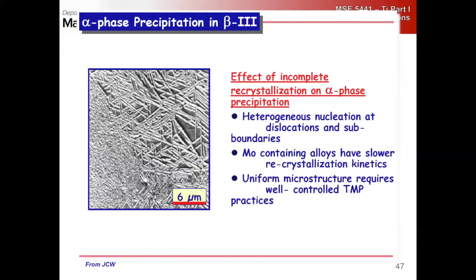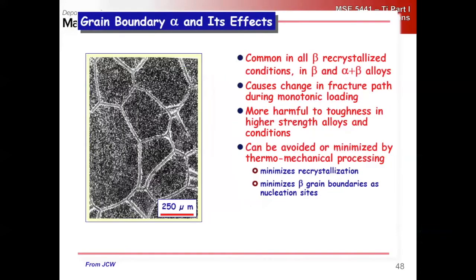We want to prevent any of that from happening, and so the main knob to turn for that is the molybdenum content in the alloys. So molybdenum becomes quite an important beta stabilizer from that standpoint. Okay. So grain boundary alpha we've talked about. It's difficult to avoid in all compositions, especially alpha plus beta alloys. But you do still see it in beta alloys sometimes.